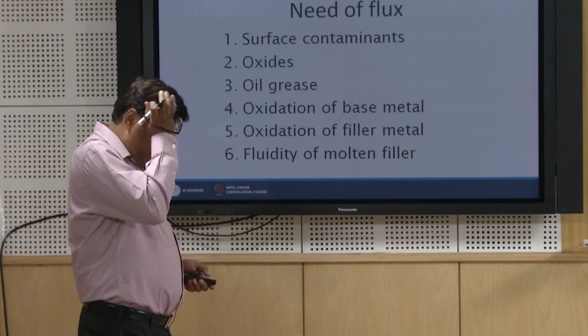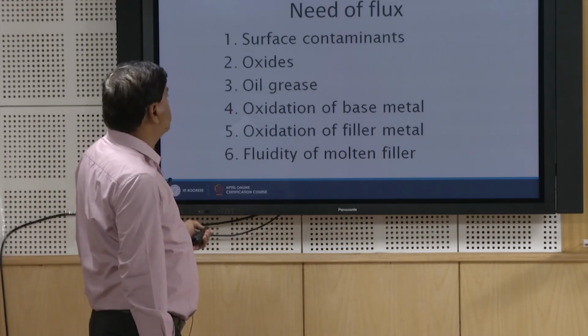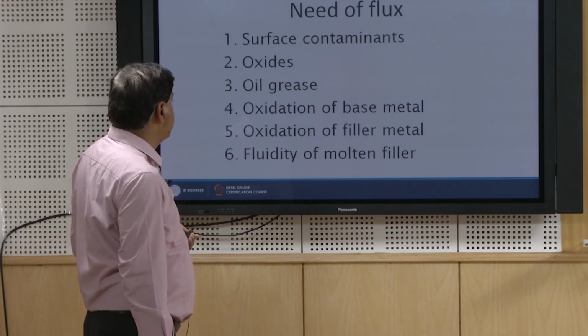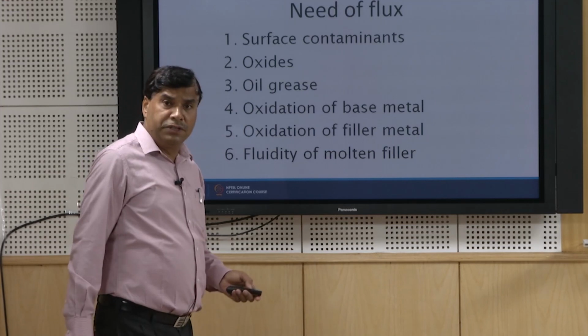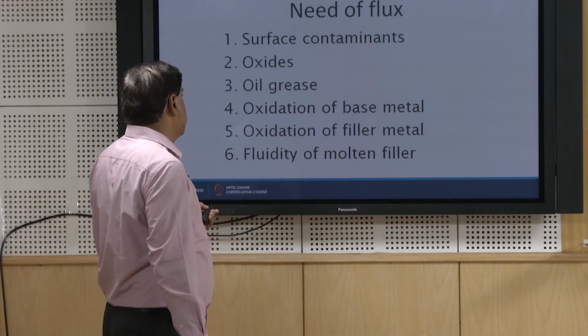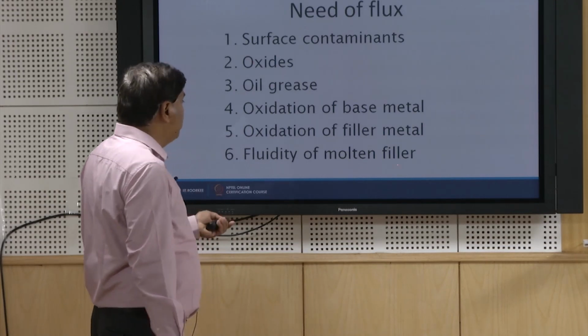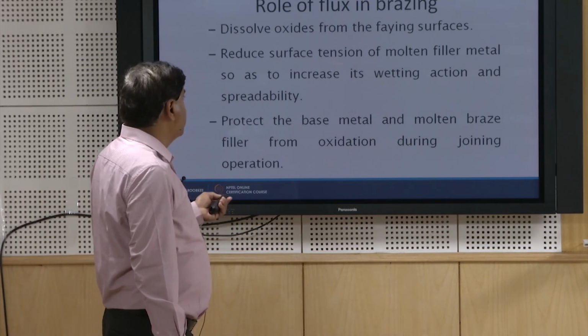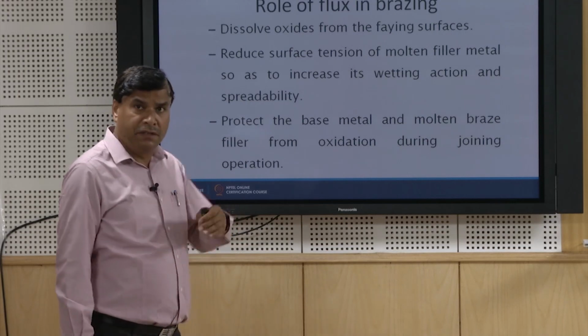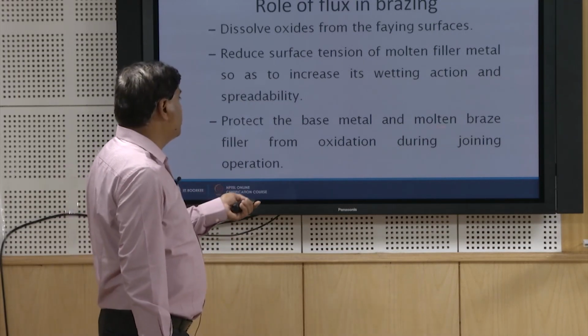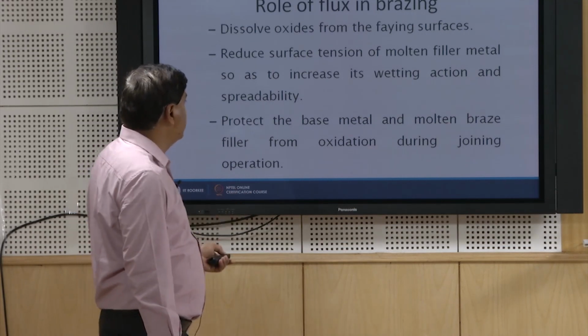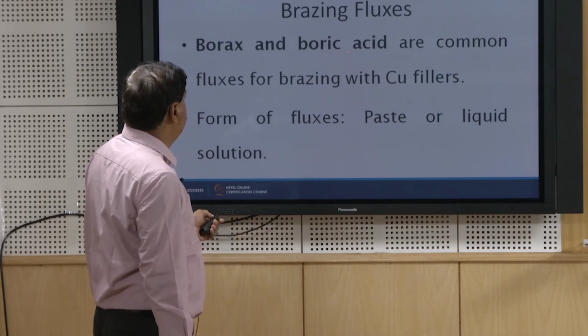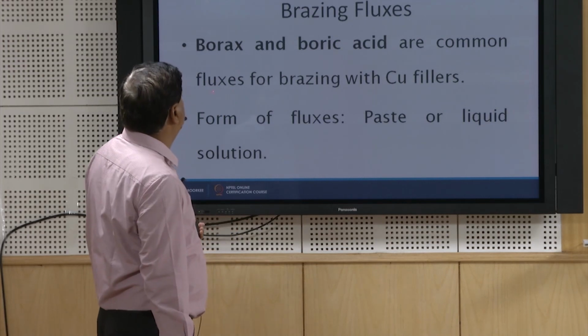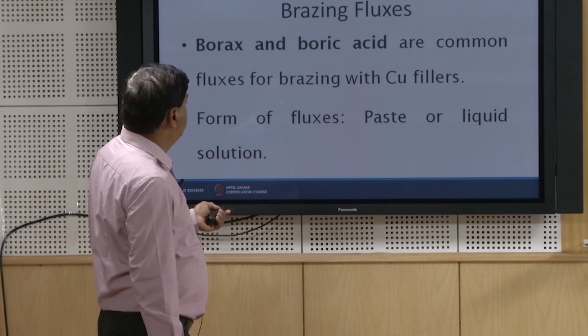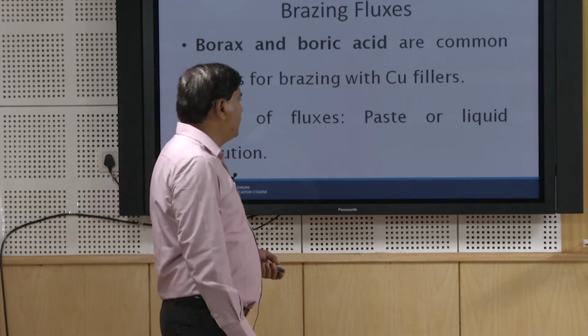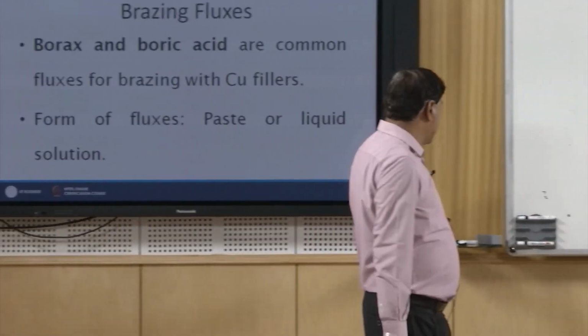These are the different purposes for which fluxes are used. They take care of the surface contaminants, oxides, oils and greases, oxidation of the base metal, oxidation of the filler, and fluidity of the molten metal. The fluxes help to dissolve the oxides from the faying surfaces, reduce surface tension in order to improve the fluidity, and protect the base metal and the molten filler metal from oxidation during the joining operation. The common fluxes are borax and boric acid, commonly used for brazing with copper fillers, and these fluxes can be used in the form of pastes, solutions or powders applied over the surface.